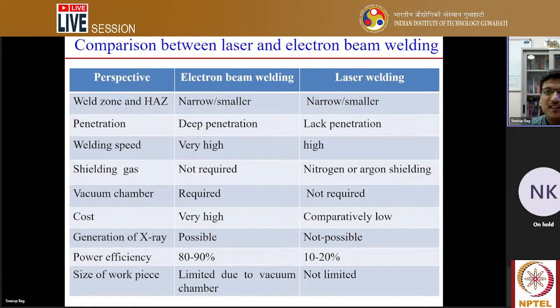Now we try to compare the laser and electron beam welding processes. Mostly you can see that the electron beam welding process gives a very narrow weld zone and heat affected zone, and laser also, but not as narrow as compared to the electron beam welding process. Deep penetration can be achieved in the electron beam welding process. Even in the laser welding process you can achieve deep penetration, but I have written less penetration because, as compared to the electron beam, this penetration depth can be less in case of the laser welding process.